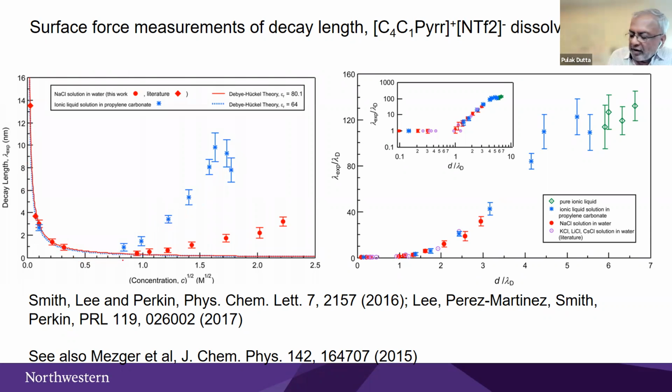And Perkin also studied sodium chloride and found the same tendency. It goes up at high concentrations, where you expect the theories to fail. Indeed, it fails; it goes right back up. It turns out, and I won't get into too many details, that if you scale it by the size of the ion, then the blue and red curves all fall together on the same picture.